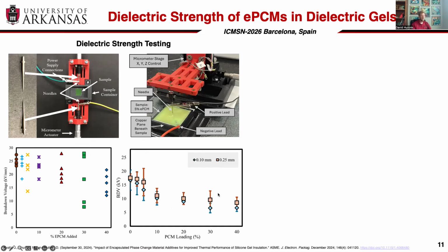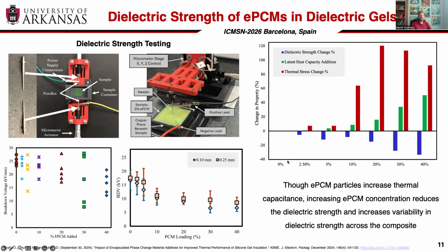However, even though we see about a 50% decrease in that breakdown voltage, the good news is that we're still seeing that this breakdown voltage exceeds that of air. So we're still seeing a benefit relative to no encapsulation whatsoever. And so this really points to some of the trade-offs that we see in the properties.